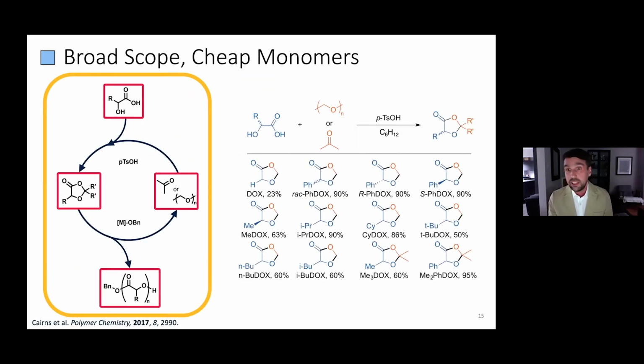Monomers are actually really easy to do. So we do some scale up in our lab, up to 5-liter syntheses. So we can make quite a lot of this material for an academic group, I guess. And one of the important things to realize out of this is that our starting alpha hydroxy acid, we're going